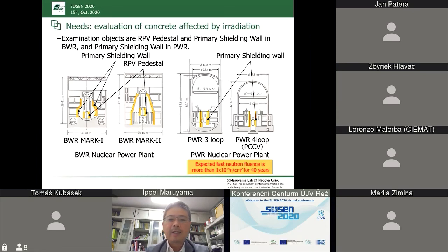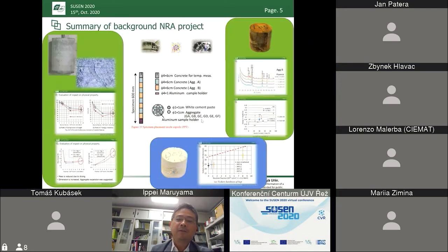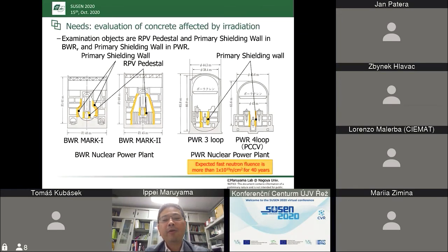Before doing the research, we used a reference value for safety evaluation. For neutron fluence, 10^20 neutrons per square centimeter is used as the reference value, which means that we think the concrete is safe if the neutron fluence is less than that value. But based on Professor Hilsdorf's paper, in some countries, regulation says that 10^19 is a critical value at which concrete degradation starts.